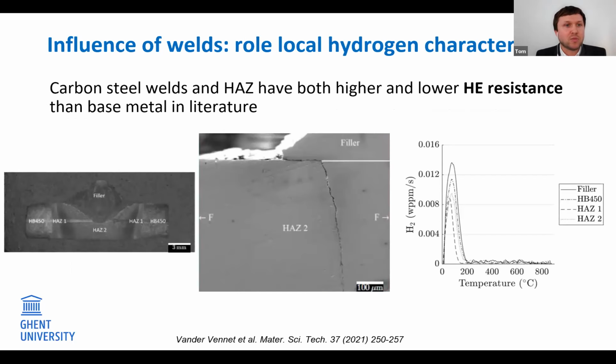We have done some work on this, and here you can see an SEM microscopy image of a weld after in situ constant load tensile testing. So we put a sample under constant load, we let hydrogen diffuse into our samples, and you can nicely see that a crack is initiating at the base of the filler. So the filler material on top, there the crack initiates, and then it propagates towards heat affected zone 2. This comes with a different microstructure, and this is then the harder microstructure.